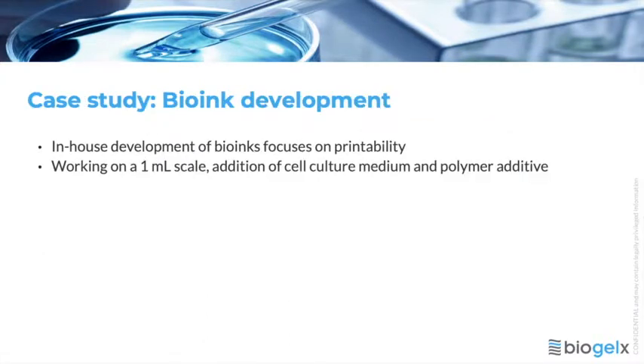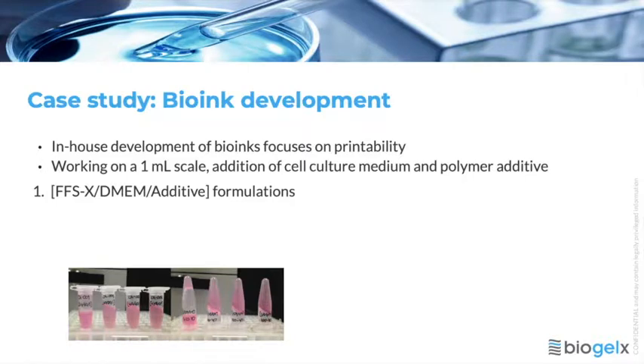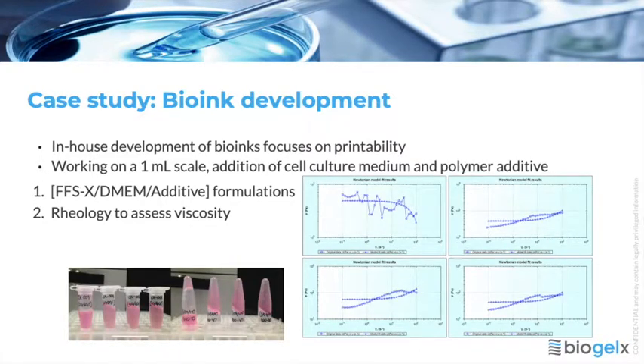So I'd like to work through a quick case study of a recent Bioink development program that we undertook. As I mentioned, we focus primarily on printability in this in-house work on quite a small scale, just making up 1 ml of each formulation at a time. And really the 3 variables that we look to optimise for are the concentration of the peptide, so this FFS-X variable. We also add in some cell culture media at this stage in Bioink development, so the concentration of the DMEM, the media that we use in this instance. And then finally the concentration of the polymer additive, which we've added primarily to get better filament formation and printability regarding that aspect.